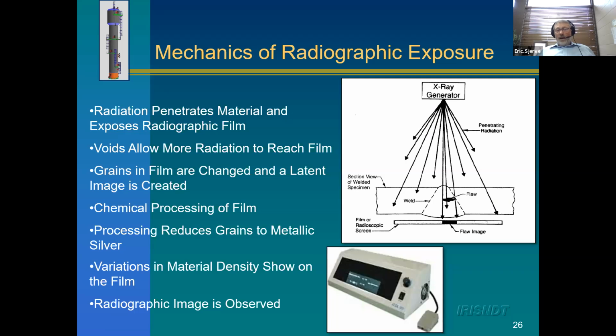So with radiography, all we're doing is we have an X-ray source or a gamma source on one side. We put the weld or the pipe or whatever we're inspecting in the middle, and we put the film on the other side. We allow the radiation to penetrate through the weld, and it hits that film on the far side. The code tells us how long we have to allow that to properly expose the film, and then we do a chemical processing on the film. I know with cameras all being digital these days, you guys probably have never done this, but it's just a chemical processing where we take a piece of film and we reduce the silver and we get a radiograph out of it.